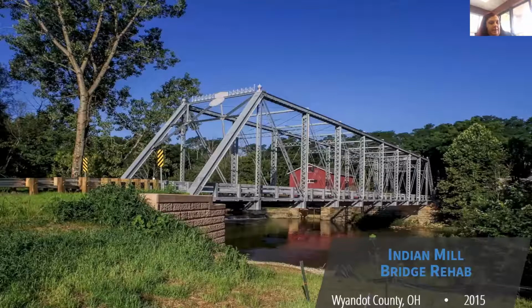This is an example a little bit different than the first one. This bridge in Ohio was, again, a structure that had been in place for over 100 years, since 1913. They had to close it in 2010 because there was some corrosion concerns or structural concerns. And so in 2015, they took down the bridge, deconstructed the existing bridge, and hot dip galvanized it and put it back into place. They did make a few engineering changes because of differences in code, but a lot of the 100-year-old steel in the original bridge was dipped and reused in the new galvanized structure.